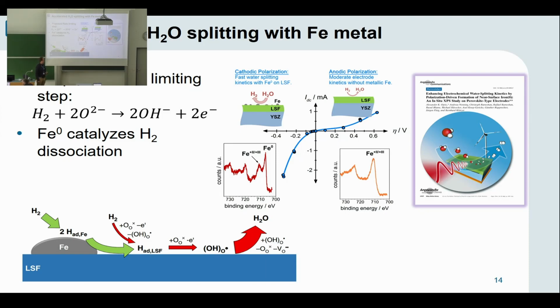And from electrochemistry, we can see that these metal iron particles are really catalyzing the water splitting reaction. And this is the reason why, in presence of metallic iron, the water splitting branch of the current voltage curve, cathodic polarization, is much faster than the anodic hydrogen oxidation reaction. And we believe that the adsorption and dissociation of the hydrogen is the rate limiting step on the pure oxide. And this process is much faster on the metal particle. And then the adsorbed and dissociated hydrogen can diffuse on the oxide surface.